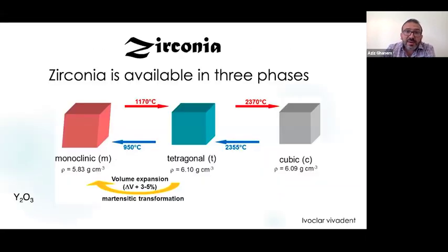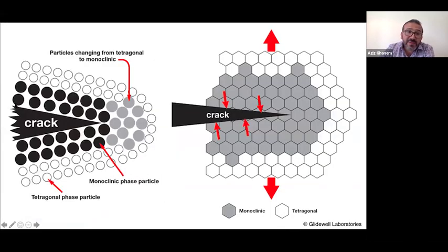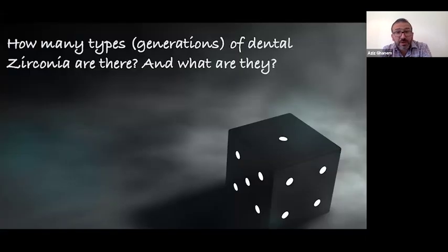So as you can see here, changing from tetragonal to monoclinic will result in an increase in volume of about 3 to 5%. If there's a crack on the surface of tetragonal zirconia, the pressure from the crack will result in the transformation of tetragonal to monoclinic phase. As I mentioned earlier, this will result in a change in the volume of the zirconia and will act as self-healing, so it will halt the propagation of the crack. And this is what is called the transformation toughening mechanism of zirconia. Simply, this explains the high strength of zirconia, mainly the tetragonal phase.